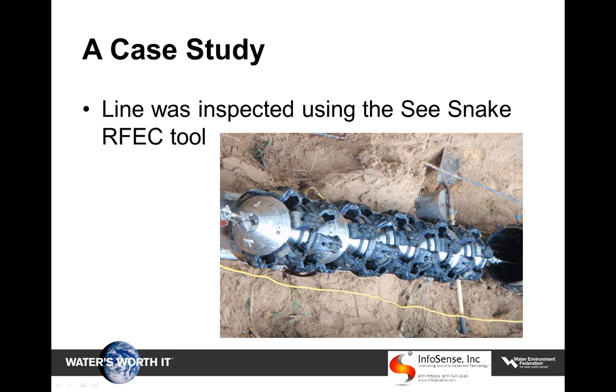Because they wanted very detailed data, we decided to use the remote field eddy current tool. It's called the See Snake, provided by PICA Corporation, which is a subsidiary of Russell NDE. This picture shows the tool just as it's coming out of the 16-inch diameter ductile iron pipe on the first run. This tool can either be free swimming or winched. Because we already had holes in the pipe for failures, it was easier to winch it through.